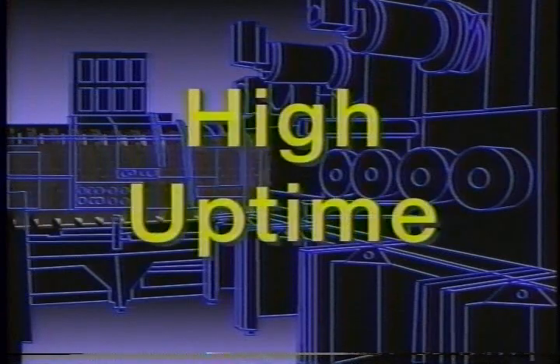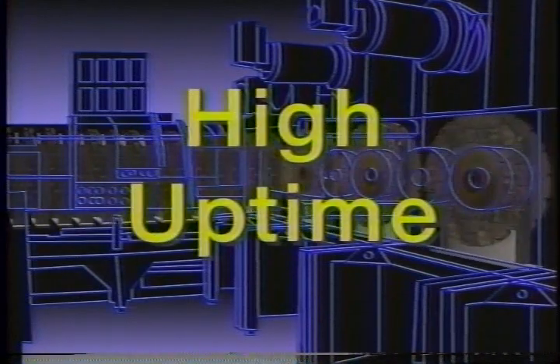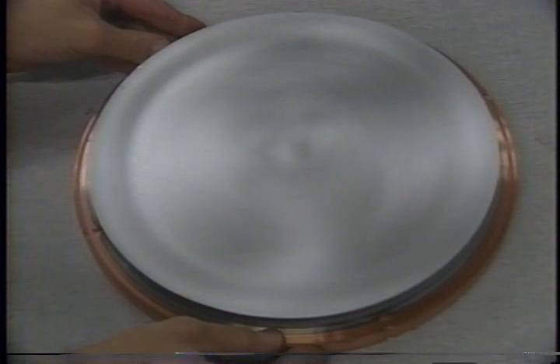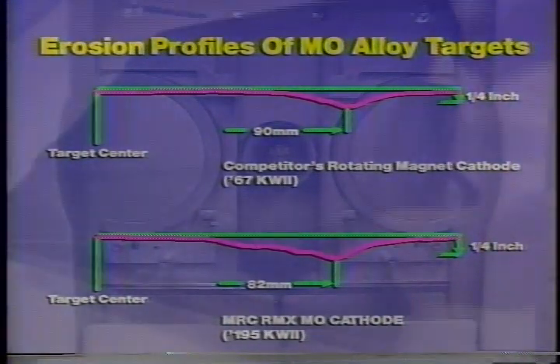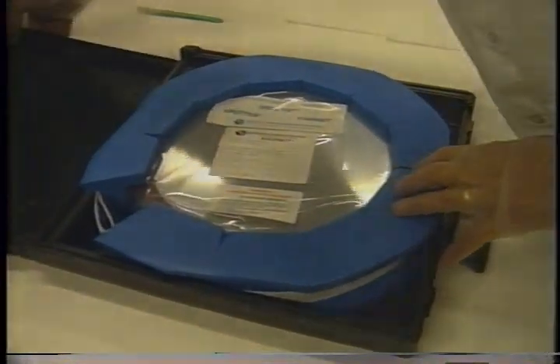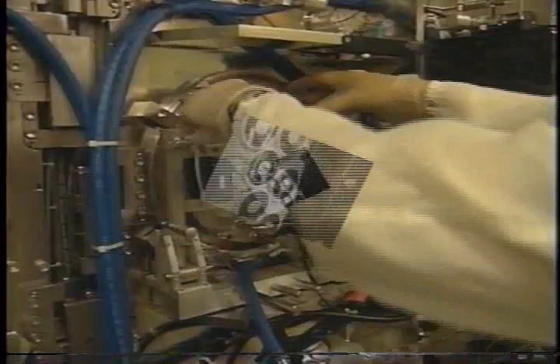With an MRC inline system, you'll enjoy high throughput day in, day out, because the people of Materials Research Corporation have mastered the art of high uptime sputtering. Thanks to the RMX rotating magnet system, target erosion is extremely uniform, so you get longer life from each target. In fact, you can run 3 shifts a day for 10 days before you'll need to replace the targets. That's a production of roughly 1 million discs before changing targets.